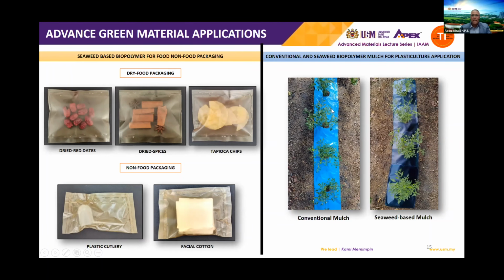The seaweed-based biopolymer was also applied in agriculture mulching. As shown in this image, we had planted chili using the conventional, the blue one, and the seaweed-based mulching. This is the seaweed-based mulching. And we found that the seaweed-based mulch directly biodegrade and compost into the soil after a certain period, whereas this is not the case with the conventional plastic. So with these applications of biodegradable and compostable seaweed mulching material, the disposal problem of the plastic waste is eliminated.